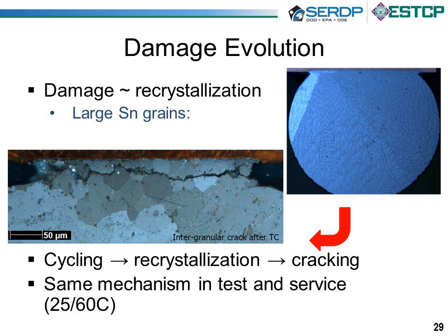And the boundaries there are actually not weak or anything like that. So if you're just going to vibrate or shear this, it will crack through the grains, not along any boundaries. But in thermal cycling, a lot of changes happen, your precipitates change, and then the grains turn into fine grains, and we recrystallize into this polycrystalline picture you see towards the bottom left there, and then the joint cracks along that. The same thing happens in pretty mild conditions, like just temperature variation from room temperature up to 60 degrees centigrade. So we're actually testing something that's likely to happen in service or in use.